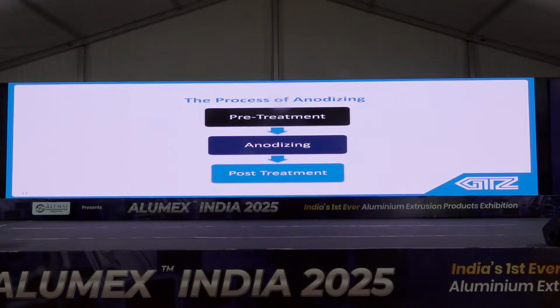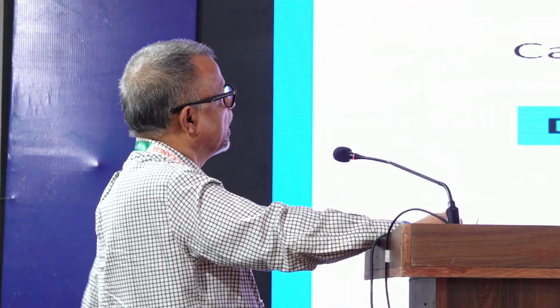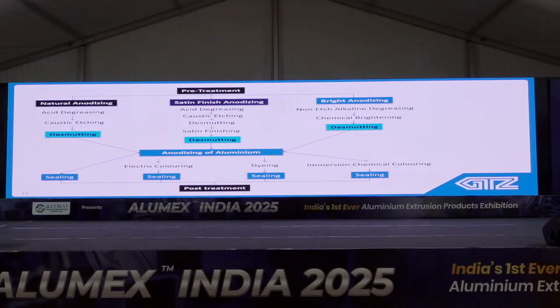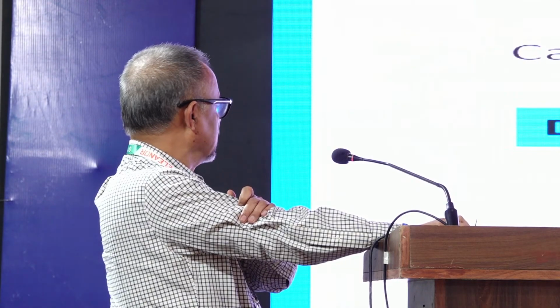The total anodizing process is pre-treatment, then main anodizing. After that, post-treatment includes coloring, electrocoloring, and sealing. So this is the pre-treatment synopsis for natural anodizing: acid degreasing, caustic degreasing, desmutting, then anodizing and sealing as post-treatment. For satin finish anodizing, one extra process is there for satin finish after desmutting, then another desmutting. So before anodizing, every type of pre-treatment ends with desmutting. Similarly, bright anodizing: non-etch type alkaline cleaner, followed by chemical brightening, then desmutting, then anodizing. For color anodizing, there is electrocoloring, possibly dyeing, and immersion chemical dyeing. But after anodizing and coloring, sealing is a must, and in every variety there is sealing. That is the last and final treatment of the anodic coating.